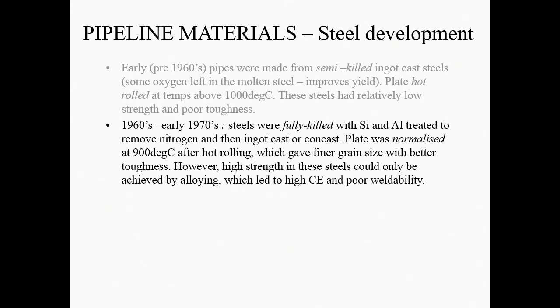So silicon and aluminium form very stable oxides. They're very thermodynamically stable. So they will gather up the oxygen quite nicely, and aluminium and silicon also react with nitrogen to form stable nitrides. So they can be reduced by that method as well. So this is done in the melt, so that by the time you get to casting, or continuous casting, and we'll talk about that later on, the properties of the material have been greatly improved.